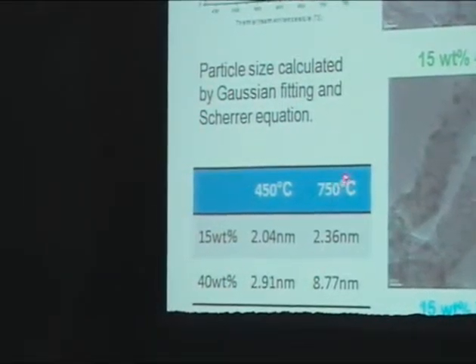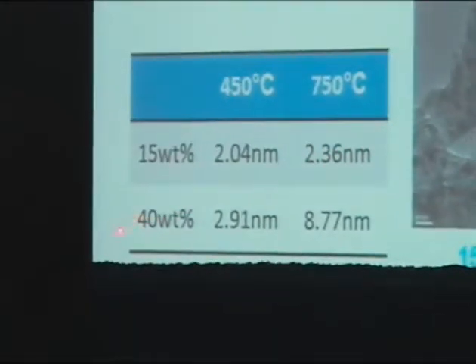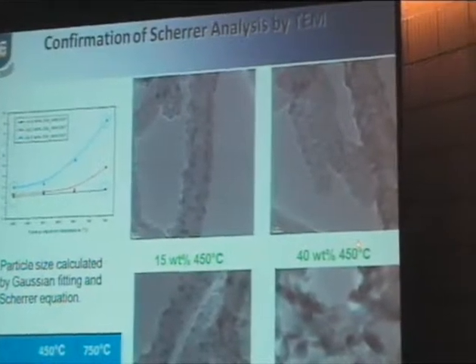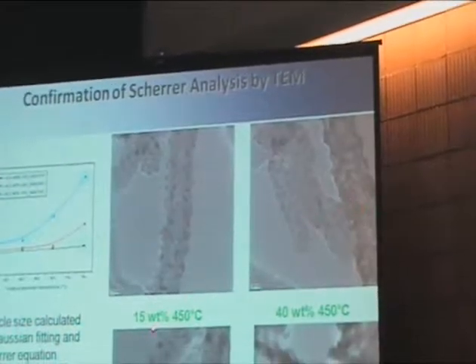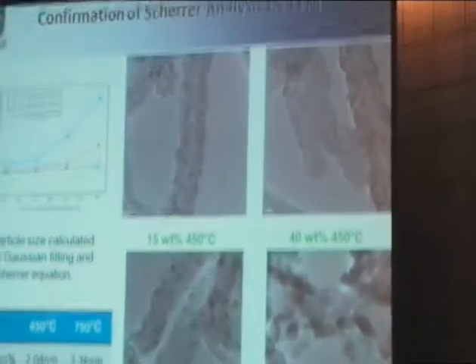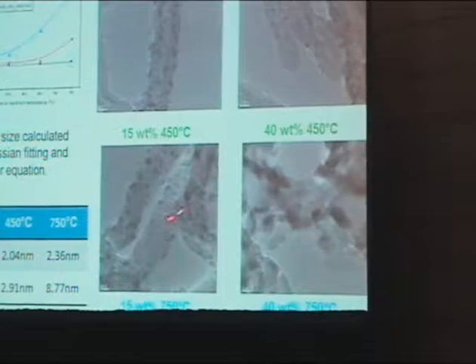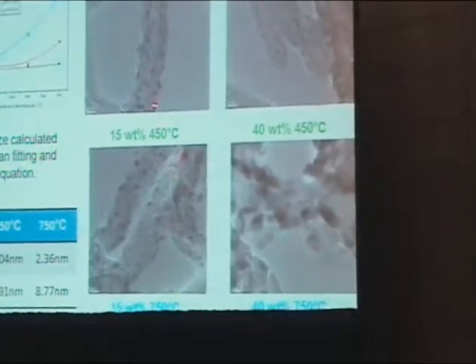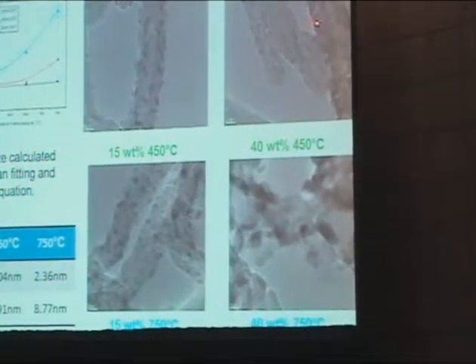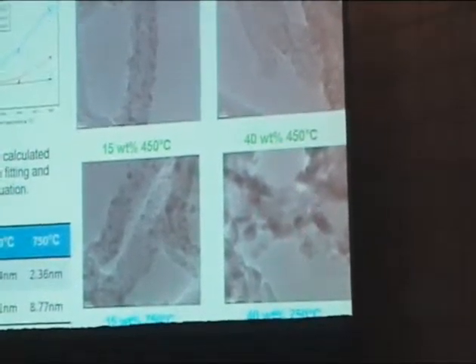That's summarized in this table, which you can read: at 450 and 750, stable at 15 weight percent, and unstable towards sintering for 40 weight percent. Or you can also see it in TEM. At 450, the temperature at which they've been synthesized, the particle size is not different at the loadings, but after we sinter at 750, which is just barely on, you'll see that the low loadings stay more or less constant, but the large loadings give us larger particles. So both by TEM and X-ray diffraction, we show that they're unstable.